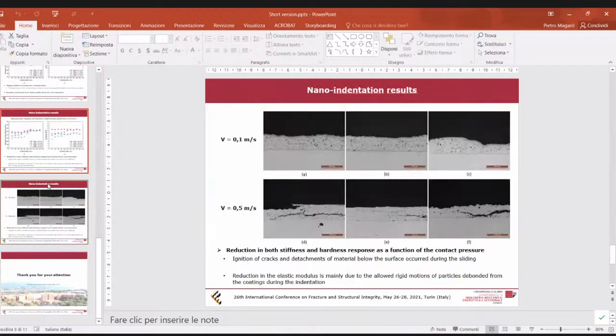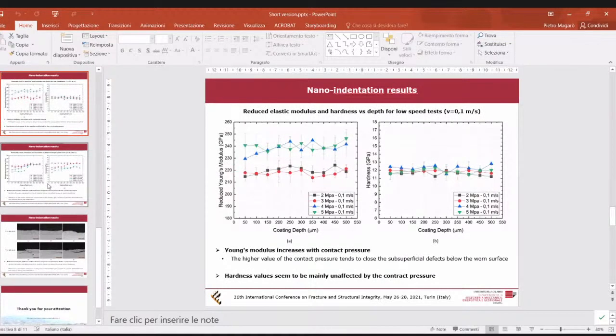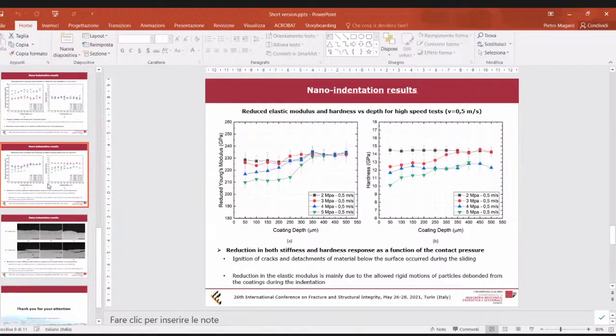My expectation depends, I think, on the damage mechanisms that could be mainly present in the case of the wet contact. I think that in the case of the wet contact, also increasing the sliding speed, the wear mechanisms should be mainly abrasive, also in the case of high speed. So I expect that the evolution of stiffness, of the reduced Young modulus, is more likely similar to these results and not similar to this one, because this evolution can be attributed mainly to adhesive wear.